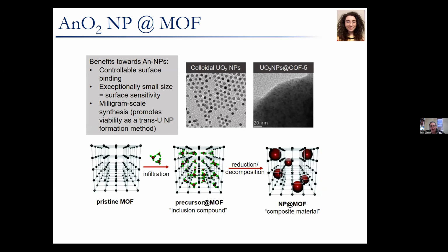So this has been demonstrated before, where uranium dioxide nanoparticles were grown inside the pores of a covalent organic framework, which is slightly different than a MOF. The general approach that they're taking is they have a pristine MOF and then they're doing infiltration of that MOF with a vapor deposition or gaseous type of loading, so that we have this precursor that is then in the pores of the MOF, and then completing a reduction or decomposition step, which usually consists of heating the material for a given amount of time that will convert the precursor into the nanoparticles. And I know this is something that Leanne and her students are working on a lot right now, and recently had beam time at APS to study their products.